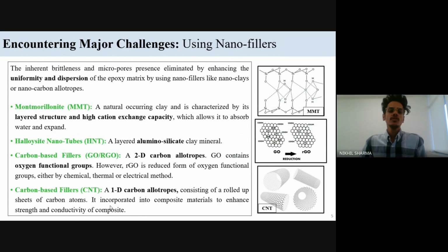To address these challenges, we use several nanofillers, which improve the uniformity or dispersion of the epoxy coatings and help eliminate their defects. For example, montmorillonite, a naturally occurring clay characterized by layered silicate structures and high cation exchange capacity, is used as a filler for the epoxy coating. Similarly, halloysite nanotubes and carbon-based fillers like graphene oxide and reduced graphene oxide, a 2D carbon allotrope. Graphene oxide, GO, contains oxygen functional groups, whereas RGO is a reduced form of GO. Similarly, CNT is a 1D carbon allotrope, rolled sheets of carbon atoms, used to enhance the strength of the composites.